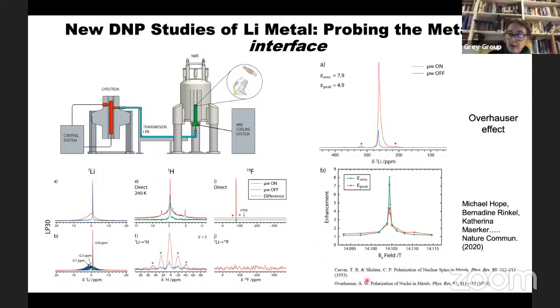And so this was largely forgotten about between '53 and 2020, when we decided we would go back and think about, could we use this to study our batteries? In the intervening almost 70 years, we have much higher fields, but actually for this, it's not necessarily an advantage. So we were able to replicate the Overhauser effect for lithium metal in our dendrites, and we get modest enhancements of signal.